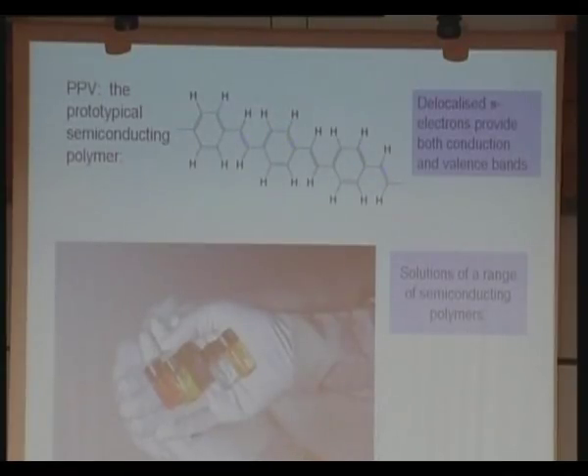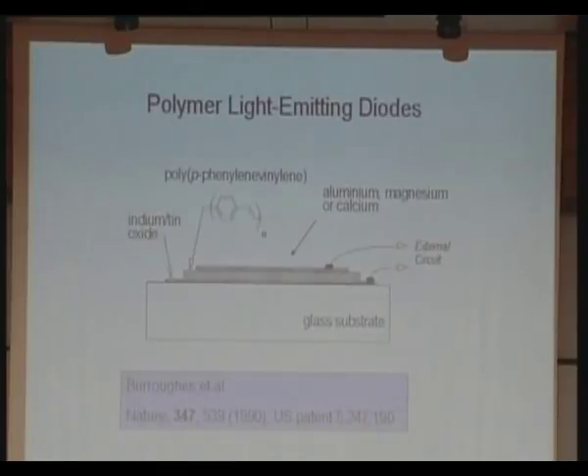And the reason for that is that they're absorbing, they're exciting the pi electron system, exciting across from filled pi to empty pi star. That is then creating a bound state, a molecular excitation, which you can call an electron and a hole if you want to, but it isn't really a free electron and hole. It's quite strongly bound, and it's re-radiating. So these are materials where once you've got an excitation, they naturally want to radiate. So the challenge is, can we get the same excitation, the same radiation, not by photoexciting, but by electrical excitation? And that's something which turns out to be much easier than one might have expected.